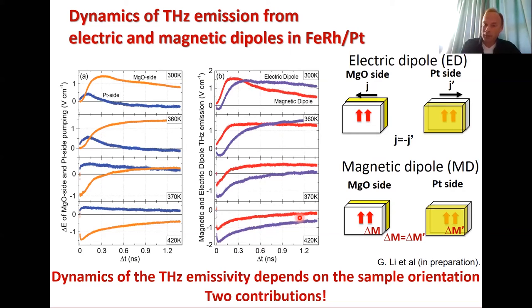It happens because when the first pump pulse arrives, it partly demagnetizes the medium. When the second pump pulse arrives, the medium is already partly demagnetized, so it can demagnetize less. As a result, the terahertz emission will be less intense. But while you separate the two pump pulses from one another, you give the medium more time to recover, and then there will be more and more material to be demagnetized by pump two. This way, you see here a fast decrease and recovery, which basically reproduces ultrafast demagnetization and recovery of the ferromagnetic state.